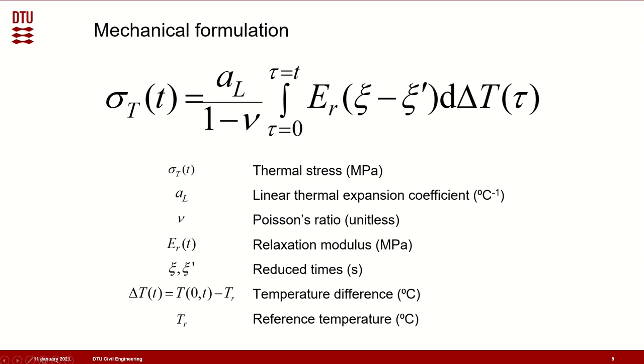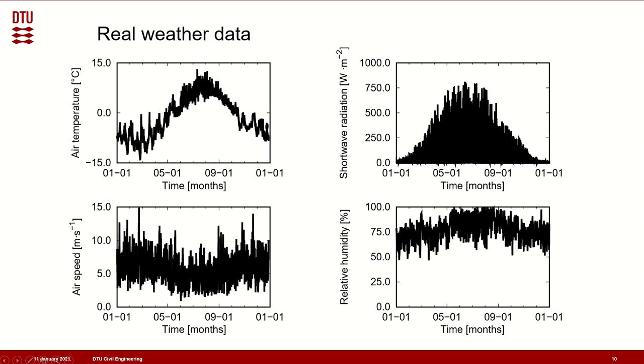The mechanical formulation aims at quantifying the thermal stress history specifically in the xy plane, where the low temperature cracking typically occurs. For this, a linear viscoelastic solid constitutive relation is selected, governed by a one-dimensional relaxation modulus and a Poisson's ratio. This linear viscoelastic formulation utilizes the time-temperature superposition principle, assuming that the asphalt material in layer 1 is thermorheologically simple. The weather effects introduced in the thermal formulation are quantified by utilizing real weather data measured by a weather station in Nuuk, Greenland.